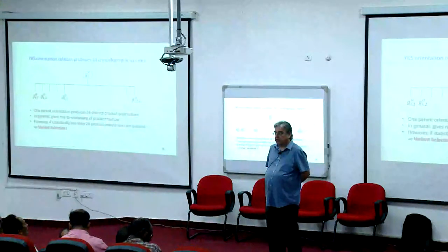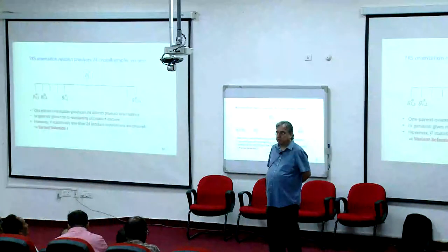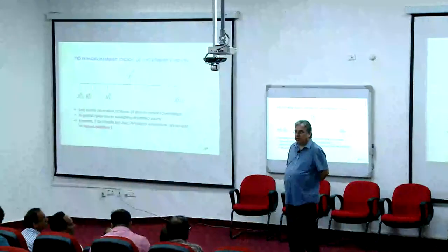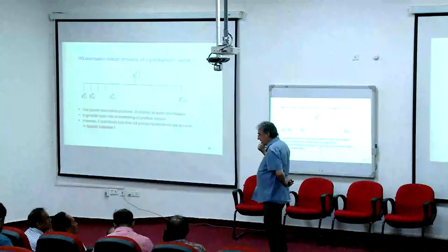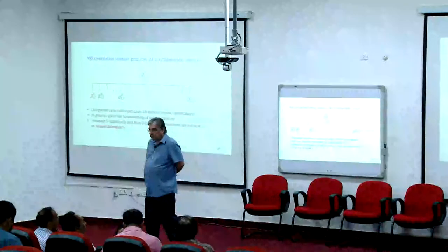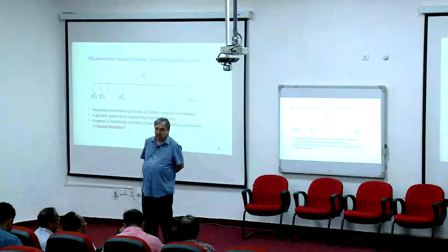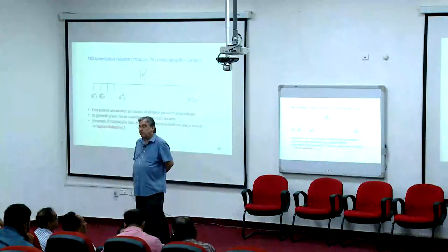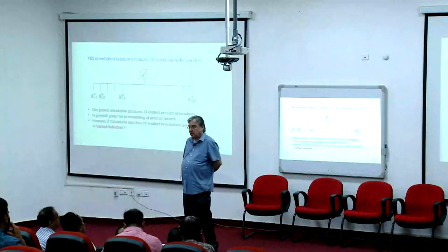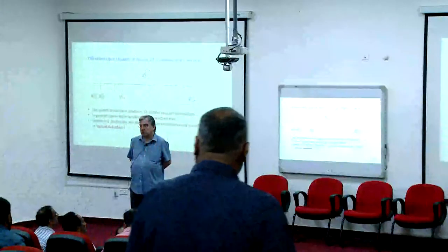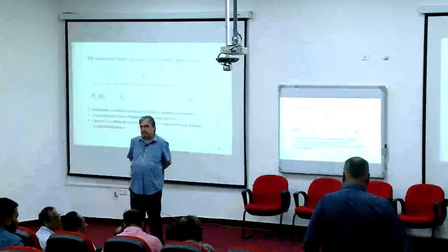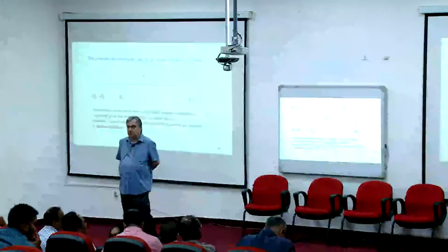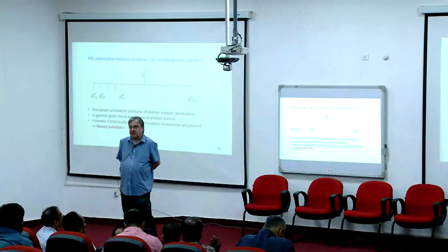Phase transformation is a very complicated process, can be a complex process. There are different types of phase transformation. And you have a starting microstructure and a finishing microstructure as a function of time. And the model that I have, in this part of the presentation that I did not give, focuses on the change of texture. You have an initial texture and you have a final texture. And that model can predict from the initial texture the final texture, but not the kinetics. It doesn't give you anything about the time it needs. It doesn't give you anything about the temperature dependence. So there is no one single phase transformation model. There are many, many different phase transformation models that predict or simulate various aspects of phase transformation.